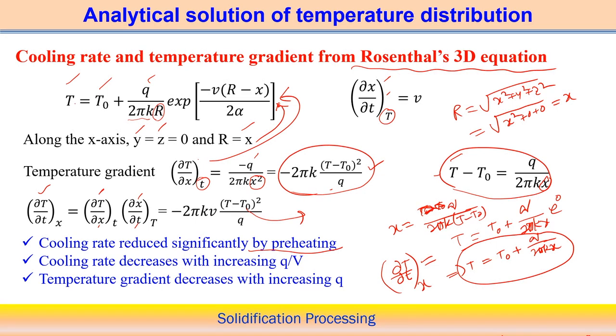In other cases, we can see the cooling rate also decreases with increasing q by v. So q by small v here. This expression can also be written as minus twice pi k (T minus T0) square divided by q by velocity v. Q by velocity v, sometimes we represent, is basically the heat input per unit length to the system. When the heat source is moving, we consider this parameter, not only the heat input but also the velocity, and q by v indicates the total heat input per unit length during this process. So we can say that q by v is the heat input per unit length.